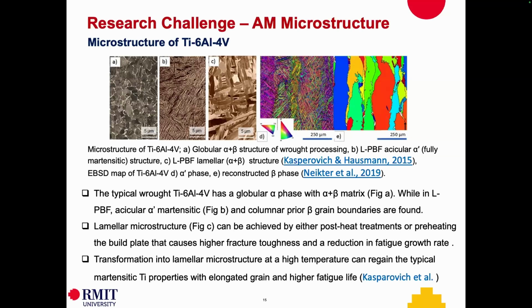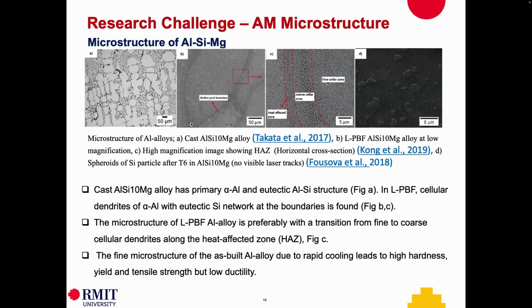You can achieve within AM of titanium alloys a lamellar microstructure by post-heat treatment or preheating the base plate. A preheated base plate acts as a heat treatment, an in situ heat treatment. Fine microstructure, particularly with as-built AL alloy, happens due to rapid cooling, which leads to high hardness, yield, and tensile properties.